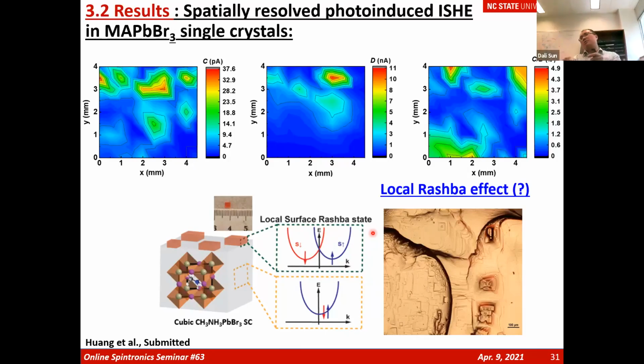If you look at the optical image which we collected, it's a very perfect single crystal by eye. Under the microscope, you still see multiple domains, multiple twin clusters. There's still the same composition, but different structures. Even this pyramid contains local symmetry breakings. But that's just me saying that local symmetry breaking, right? Because it still contains the lead. There's no evidence to prove our hypothesis.